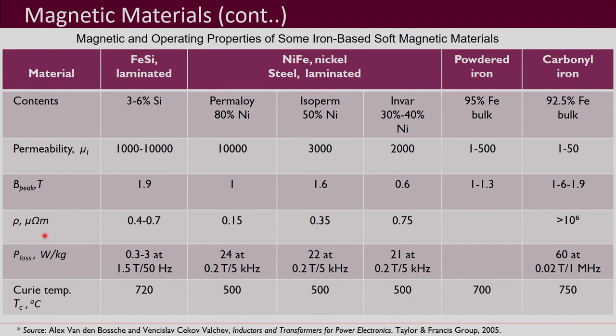Regarding resistivity, it should be as high as possible. Most of these materials have lower resistivities, whereas carbonyl iron has very good resistivity. For P-loss, which should be as low as possible, iron-silicon has very low P-loss — measured at 1.5 T and 50 Hz — making it especially suitable for 50 Hz power transformer applications. For Curie temperature, iron-silicon and carbonyl iron have very good values, and powdered iron also has a very high Curie temperature.